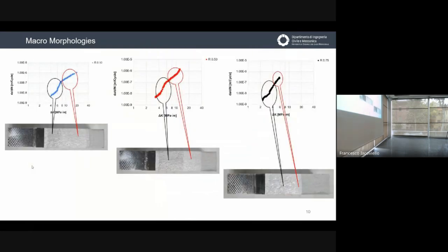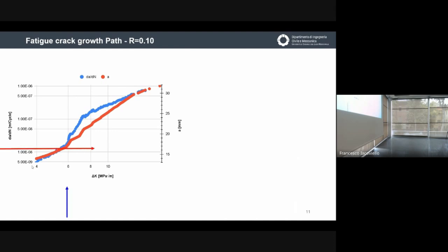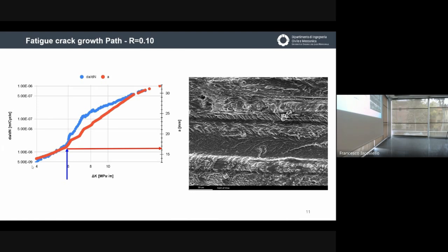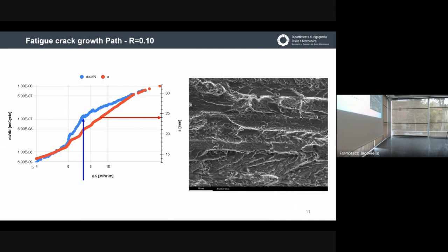In terms of correlating the da/dN versus delta K curves with the surface, you can see that the first and second stage characterize the first part of the microstructure, then the white zone in all the cases. So we investigate what happens when the slope changes. Here, at low values of delta K, you can see that the mechanisms are different in the different phases. This is the direction of the crack propagation. And at the end of the second one, we always have the same direction. When delta K changes, the difference between the different phases tends to be homogenized.